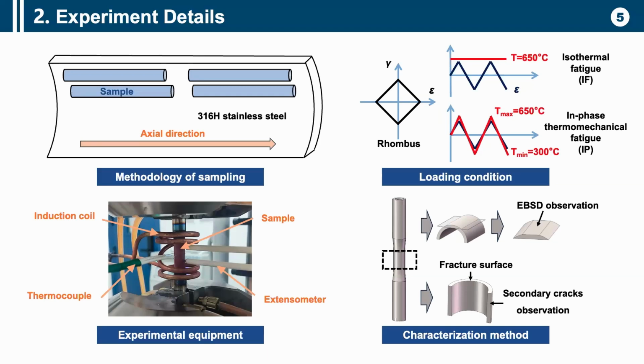These are 90 degree out-of-phase tension and torsion loading paths. And we have two loading conditions: isothermal fatigue, which we call IF, and in-phase thermomechanical fatigue, which we call IP. For IF loading, the temperature is constant, kept at 650 centigrade, and the strain is cycled. But for in-phase thermomechanical fatigue, the maximum temperature is 650 centigrade, the same as the IF loading, but the minimum temperature is about 300 centigrade.